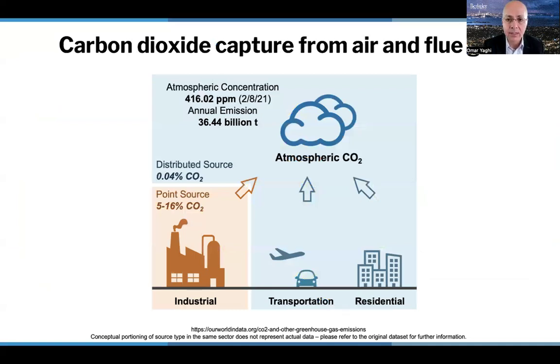So let's talk about carbon capture. Here, the problem could be divided into two parts. The problem of taking CO2 out of the air, where you have one CO2 molecule for each 2,500 molecules in the air, so you have to pluck it out of the air selectively, or in other words, it's 0.04% by volume of the air. Or from point sources, where if you burn natural gas, you're emitting about 5% CO2 by volume. Or if you're burning coal or petroleum, the CO2 levels could go up to 16% by volume of the flue gas. So these are two problems that we need to be able to address. And I'll show you how MOFs and COFs have been able to do this.